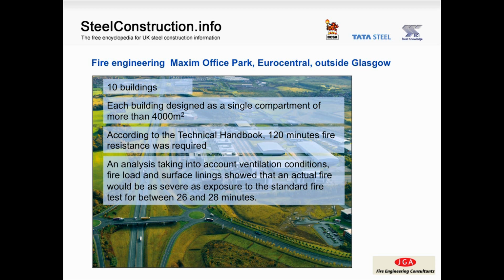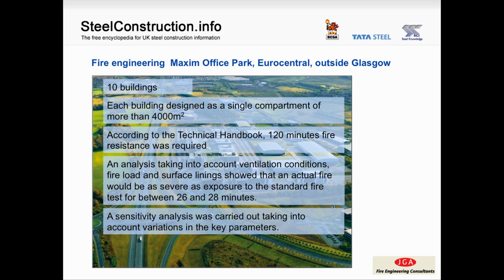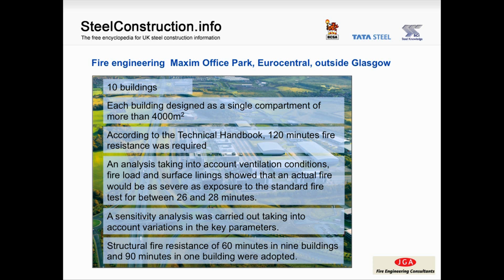The engineers calculated that at the time equivalent of the buildings, the severity of the fire compared to the standard fire test was just short of 30 minutes, sometime between 26 and 28 minutes. A significant degree of conservatism was introduced into the calculations by making assumptions as to unfavourable variations in certain parameters. For example, ventilation conditions were changed to reflect the most onerous conditions. These might occur, for example, if all the windows did not break. In the end, reductions in fire ratings to 60 minutes were accepted in 9 of the buildings and 90 minutes in one of the buildings.